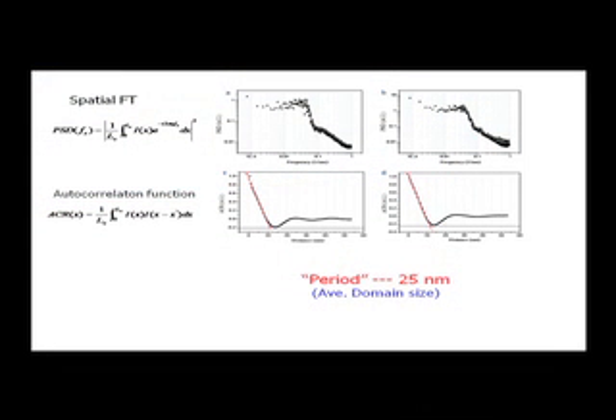I can take this system and I can take, of course, all digital information. So I can take a scan across here, and scan across here, and scan across here, and take all that data and I can average it and I can start doing some calculations. I can calculate, for example, the intensity here times the intensity a little ways away, and then I can integrate over that separation. That's called the autocorrelation function. And here's a plot of the autocorrelation function from those data. Okay. Autocorrelation function, of course, starts off at 1, because when the 2 points are at the same place, then they're correlated. But the question is, how fast do they fall off, and is there any semblance of periodicity?